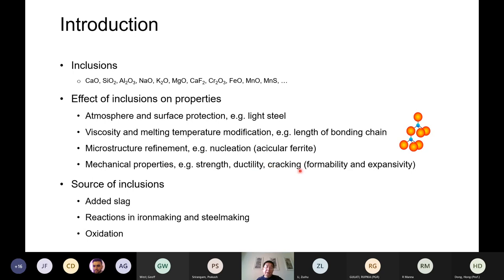But one of the major things is cracking. If you have those inclusions, the cracking gets much easier because those inclusions have different properties compared with liquid steel. For example, their formability is different. So if you do rolling, they will not deform at the same rate as the liquid steel, which generates a crack. And also the thermal expansion coefficient is different. So if you get a temperature change, those inclusions will not expand in the same way as the steel, which generates a crack.